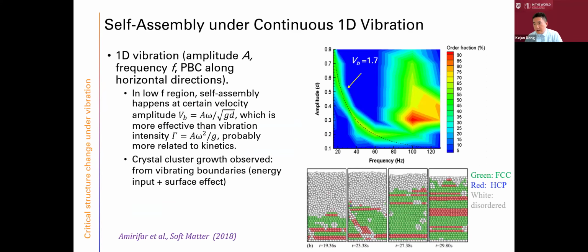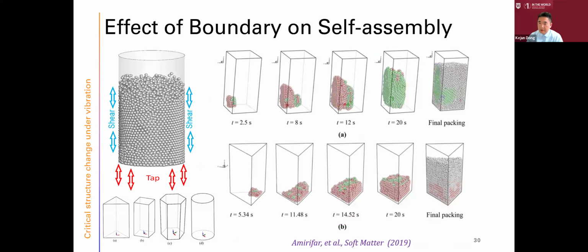Then in the follow-up study, we carefully checked the parameter space, and we understood we can also use a continuous vibration to turn the whole disordered packing into an ordered packing. Maybe not fully ordered, but we can see it will grow from the bottom to up. And then we find that if we introduce different vibration modes on different containers, we can observe different ordered packing clusters actually grow from different boundaries. So we have a boundary effect, and we have something similar to the crystallization nucleation theory, that the crystal starts from nucleation and then grows with time.